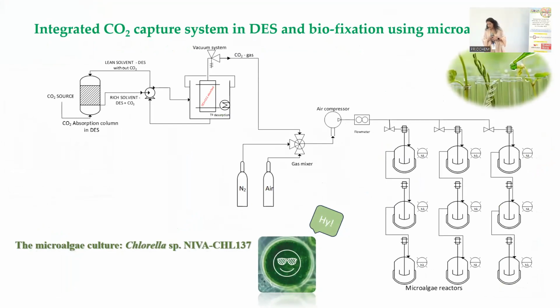We had an integrated installation where we started from an absorption column, where the CO2 was absorbed using several deep eutectic solvents. The enriched solvent was then transferred to the desorption column, where we apply temperature and vacuum in order to desorb the CO2, and after that bubble it in the bioreactors periodically, in order not to acidify our growth medium. The selected microalgae was a chlorella species from the NIVA Institute.